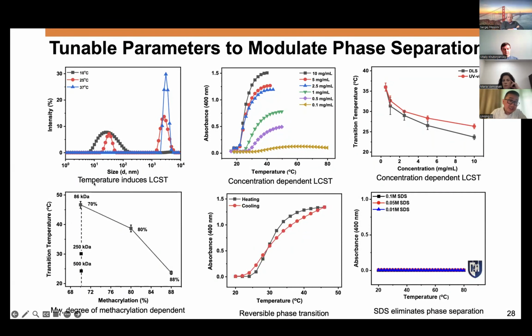Further, you can use the molecular weight to control this. As you increase the molecular weight, you lower the transition temperature. As you increase the modification, you also lower the transition temperature. We also did a heating and cooling cycle to show this is a reversible process. It's truly an LCST phenomenon. Heating is the black and cooling is the red, indicating negligible hysteresis, meaning this is a rapidly healing phase separation and dephase separation process. So this is truly LCST behavior in our system that we've been able to induce.